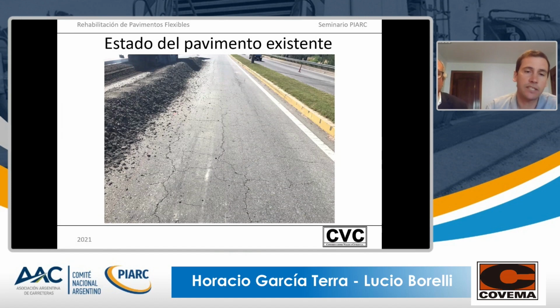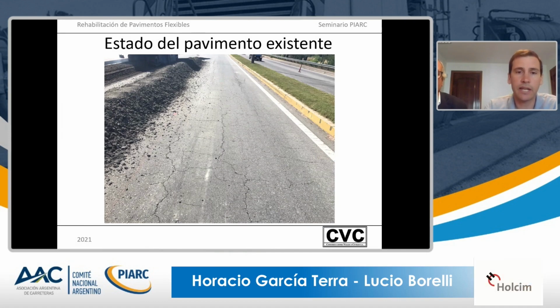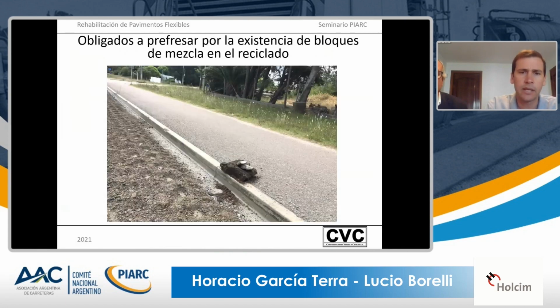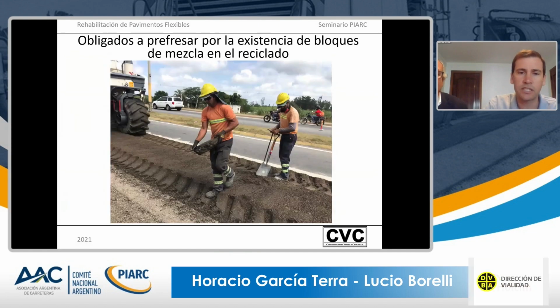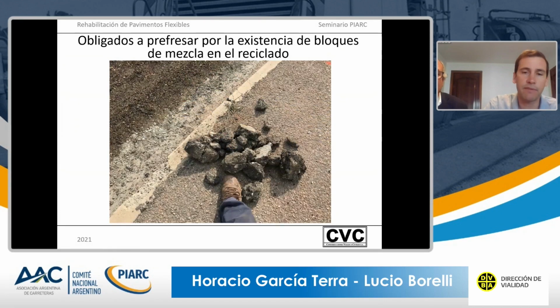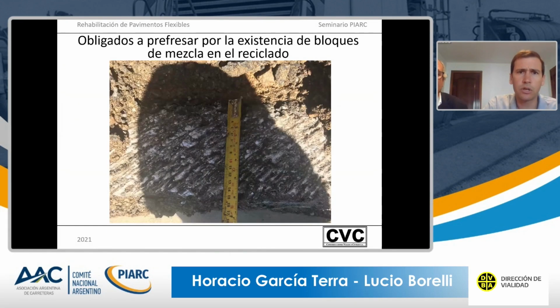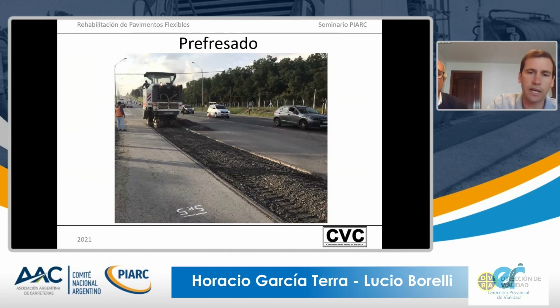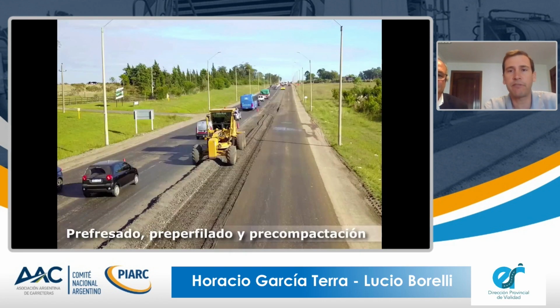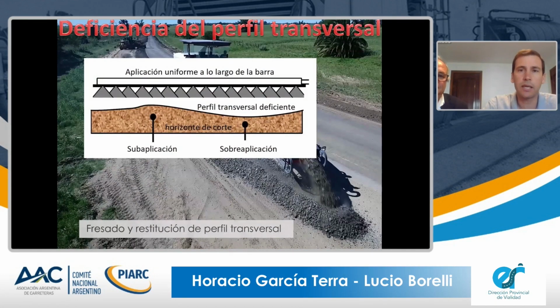we realized that when the road had to be recycled, some blocks could come off. This implied extra cost for the road administration. We were asked to do a test first of recycling with no milling, and we found out there were blocks already, and this is not desirable in this layer. So we were forced to do a pre-milling and pre-profiling and pre-compacting.